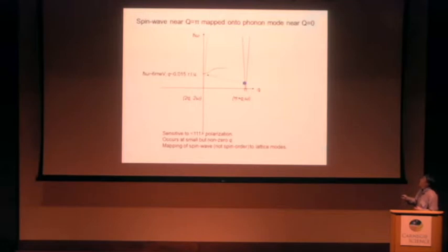So you see that near the 111 Bragg peak, that's sensitive to polarization fluctuation along the 111 direction. The other question is, why do Raman measurements not see this enhancement? Because in our neutron measurement, we have a rather coarse Q resolution. So when we measure near Q equals 0, it actually covers this small q. But for Raman measurements, this q is actually non-zero, so it's not observable by Raman measurements. So that's basically how we try to explain this.